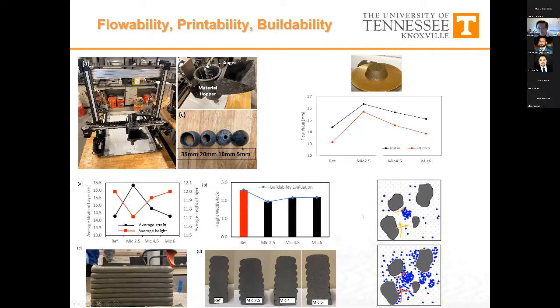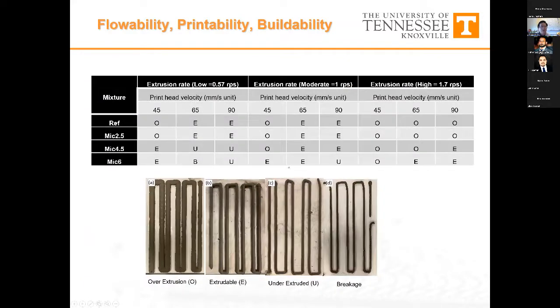One of the hypotheses that we have here is that when the volume dosage of those functional particles is low, those microspheres, if you think about them in the microstructure, almost act as a lubricant to mobilize those sand particles during the mixing and extrusion process. Whereas when the volume loading of those particles becomes higher, they start to form a jamming mechanism that hinders the movement of those sand particles, which later leads to printability issues.